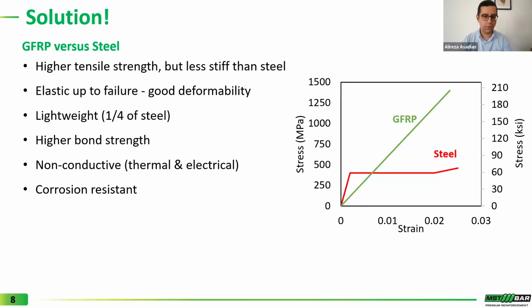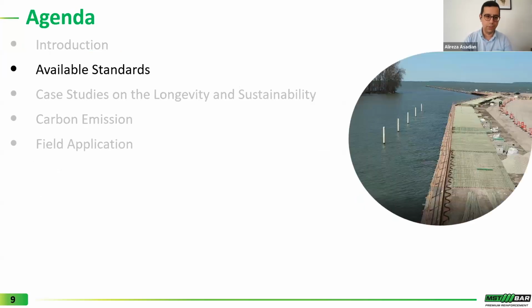MST bar and other GFRP bars are very lightweight. They weigh only a quarter of black steel rebar. Some GFRP bars, including MST bar, have a very high bond strength to concrete. GFRP bars are non-conductive, both thermally and electrically. That can be of benefit in certain applications. And obviously, as I mentioned earlier, MST bar, GFRP bars are corrosion resistant.